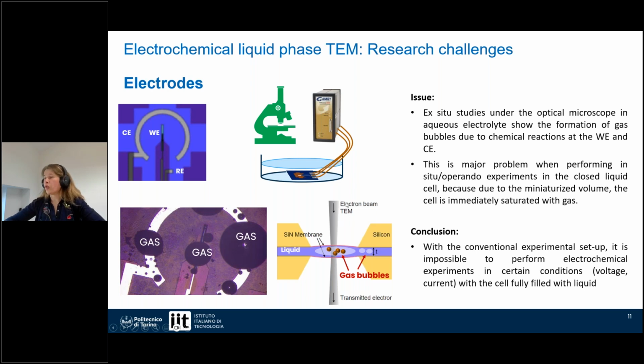So if you can imagine these big bubbles in the closed cell, where we have a little liquid, so a small thickness of liquid over the electrode in the cell, this is a major problem: the saturation of the gas, because it easily happens that this miniaturized volume of the cell is immediately saturated with the gas. We can try to mitigate this problem by various strategies.